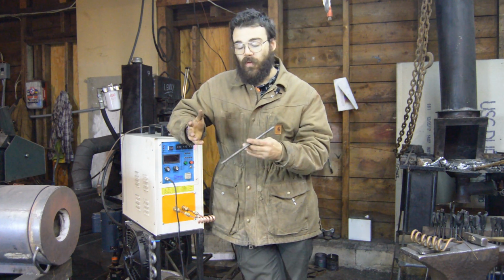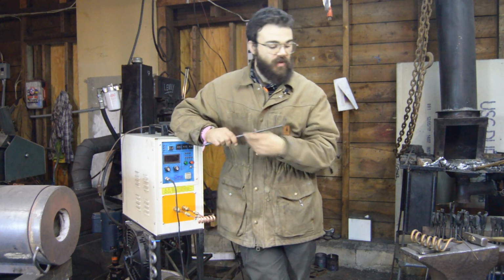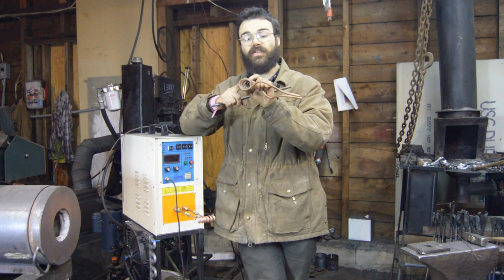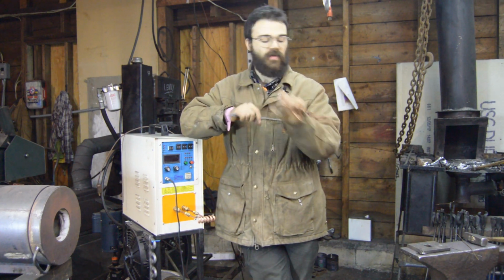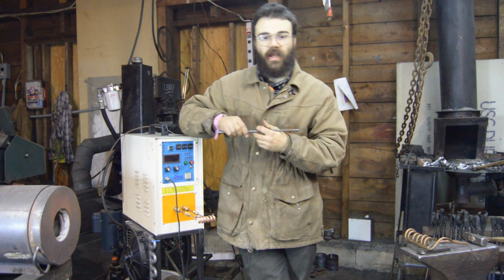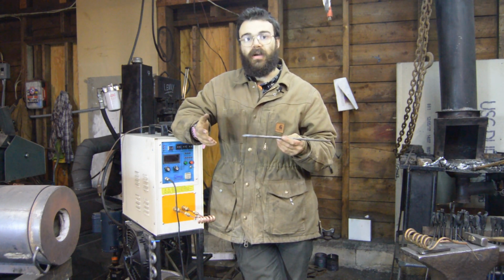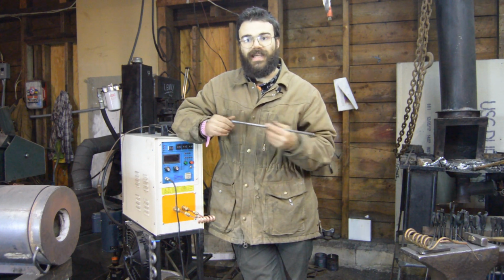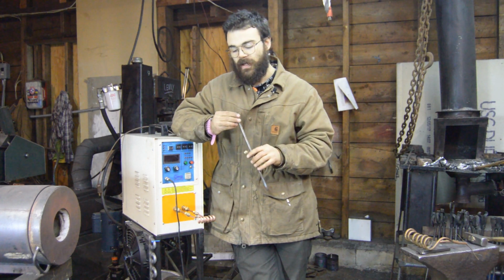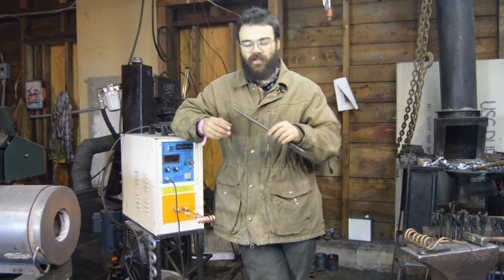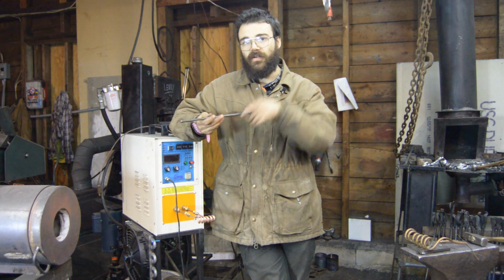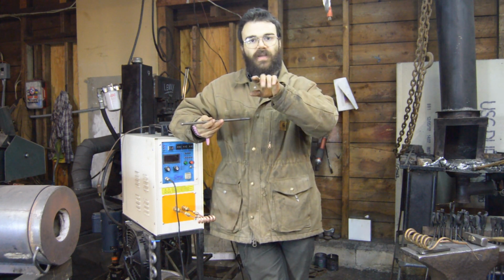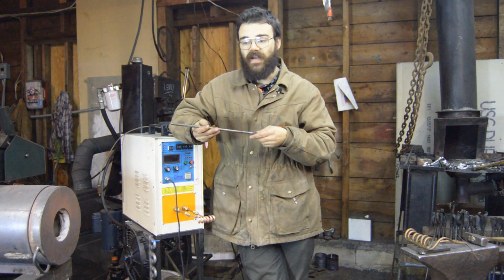So if you remember before, when I told you that the field lines are most concentrated near the surface of the coil and less concentrated at the center of the coil, it's obvious that we're going to have more of an induction heating effect at the surface of the metal. And so this will happen at the surface. If you look down the end of a long bar as you heat it, you'll notice that the surface gets hot very quickly and the center stays cold, and that's because of this effect.